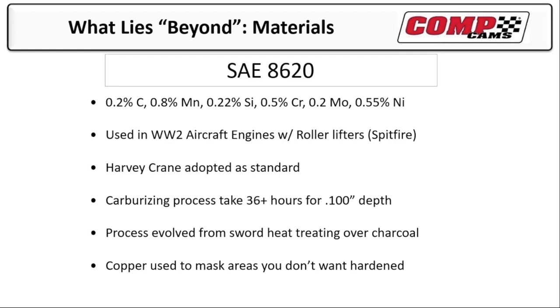Really, if you think about carburizing, if you've ever seen the old swordsmiths where they'd stick the sword into a charcoal fire, and then they take it out and beat on it and stick it back in the fire, they didn't really know what was going on. But what was happening is the low carbon steel was being penetrated by the carbon. The carbon was actually diffusing into the first 10, 20, 30, 50 thousandths of material, and that was what's creating the hardness. On 8620 camshafts, the copper on it is not to do anything except keep the parts you don't want hard from getting hard. So it's kind of neat that the copper is not an enhancement. It's not to make it look good. It's to keep the camshaft from breaking when you straighten it.